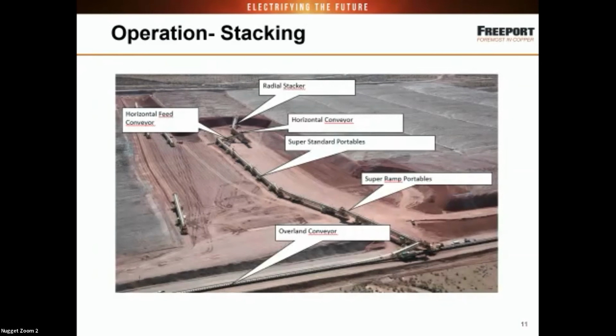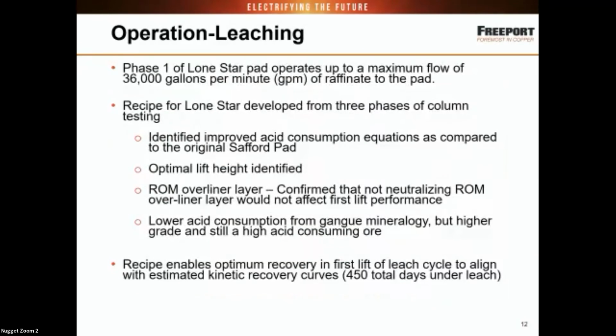Next, please. So as regards leaching, phase one of Lone Star operates to a maximum flow of 36,000. Initially, we started at that. Obviously, due to lift constraints, as the pad gets slightly smaller each lift, it has declined slightly. A recipe for leaching the pad is actually in my paper. It's not in the slides, but was determined through several phases of column testing, during which we identified improved acid consumption equations compared to our original pad, which was obviously a very high acid consumer, and we had to compensate for the calcite that was in the pad.